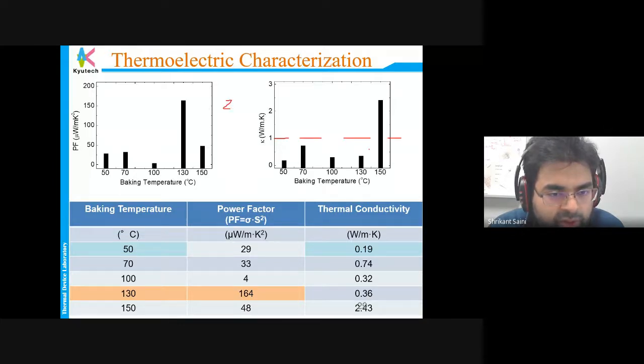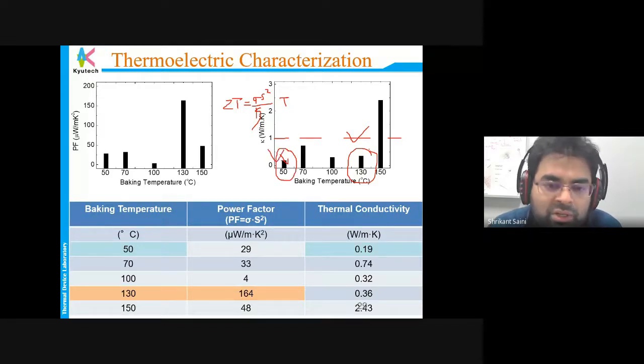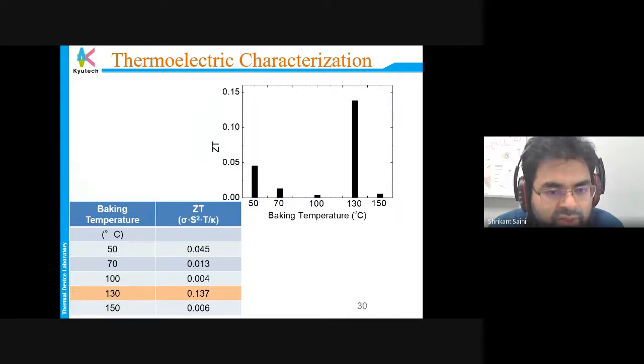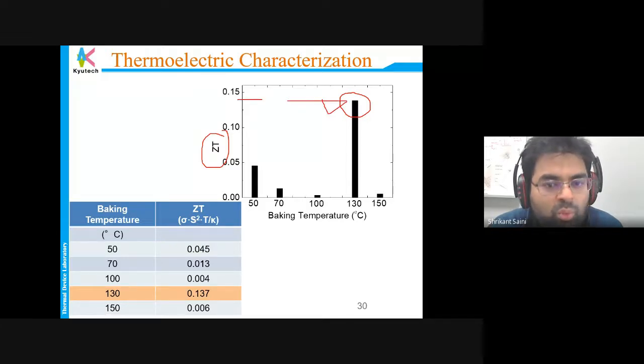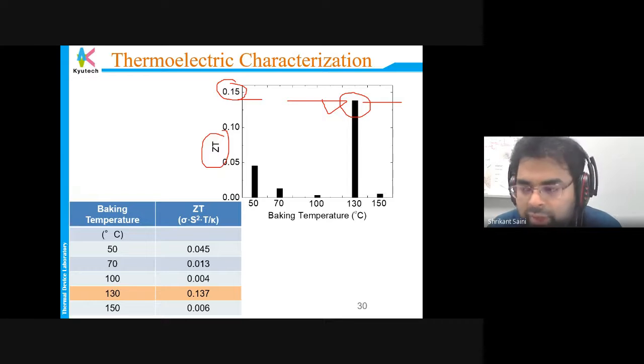If you remember the formula for ZT, it was sigma S squared, and kappa was down here. This is sigma, sorry, and T somewhere here. So you need a lower thermal conductivity, and 130 has shown lower thermal conductivity. 150 also shows the highest thermal conductivity, but this material has changed form at 150, so we will not consider it here. 130 was the best material which we chose, and when we calculate the ZT, the best ZT reported so far for this particular material is around 0.14. It's also important to note this is the ZT for a flexible material, compared with the organic materials which they are making for wearable electronics or wearable devices. This is one of the best ZT values we have got at the moment.